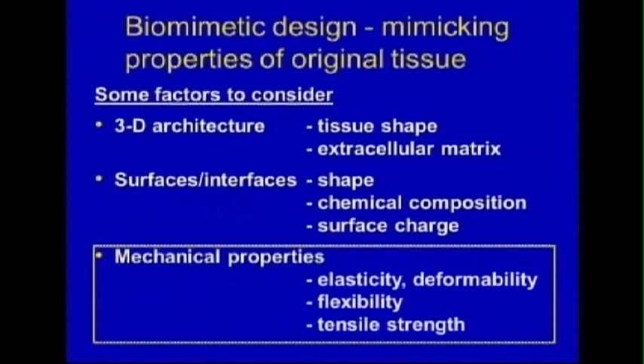Remember I said sural nerve is the gold standard. So when we do these, the control group are sciatic sural nerve. The best compound muscle action potential we can get with a sural nerve is maybe 50–60% of normal. It never is as good as normal, but that's the best we can do right now. Up till now, the best polymer that we did was perhaps 1/4 to 1/3 of what we got with sural nerve.